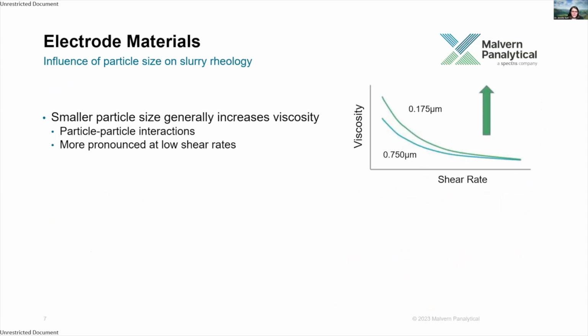And it's not just that. To produce the finished electrode, the electrode material and conductive additives are combined with the polymeric binder and solvent to form a slurry, which is then applied to a metal foil. So obviously the rheology of the slurry is important. And the particle morphology affects the slurry rheology, which will in turn affect the electrode production process. So in general, the smaller the particles you have, the higher the viscosity of the slurry, due to the increased particle-particle interactions. And this is more pronounced at lower shear rates, as shown here.